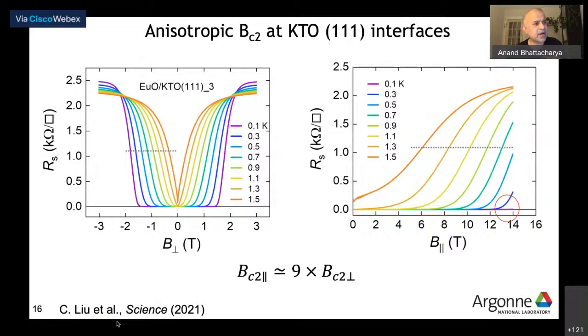Now, if you turn on magnetic fields, you can drive the superconductivity away, like you would imagine, and the critical fields are quite high. For this sample, it was well over a Tesla for out-of-plane fields. Our first evidence that there's two-dimensional superconductivity is that the in-plane critical field is much, much higher than the out-of-plane one. It's like 9 times higher. In fact, at the lowest temperatures with our 14 Tesla system, we could not actually drive the system normal.